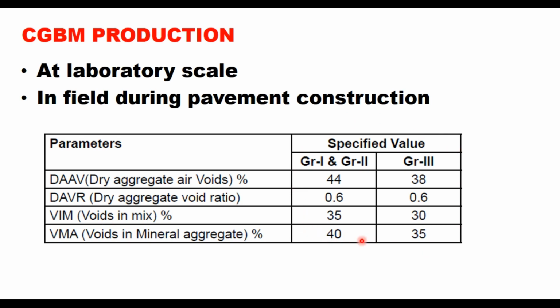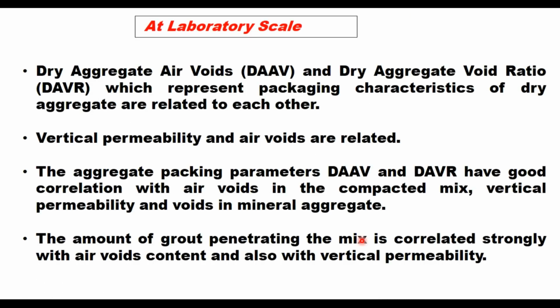Now, a few points are to be noted here. In laboratory scale production, dry aggregate air voids and dry aggregate void ratio, which represent packing characteristics of dry aggregate, are related to each other. Vertical permeability and air voids are also related. The aggregate packing parameters DAAV and DAVR have good correlation with air voids in the compacted mix, vertical permeability, and voids in mineral aggregate. And the amount of grout penetration is correlated strongly with air voids content and also with vertical permeability of the mix.